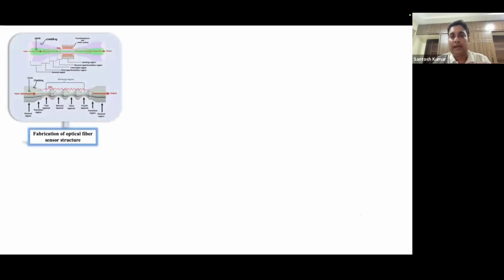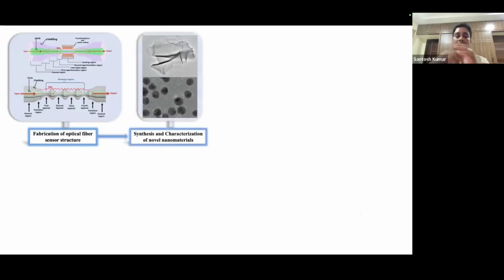So here with one schematic I will try to show how this evanescent wave sensor works. But before that I want to show one schematic of how we do the fabrication of this kind of sensor. Firstly, we fabricate the new kind of fiber structure which can give more and more evanescent wave, and that will be very sensitive. And after that we do the synthesis of the noble nanoparticles, like here the example of gold nanoparticle and graphene oxide, which we can easily synthesize with the Turkevich method and modified Hummers method.